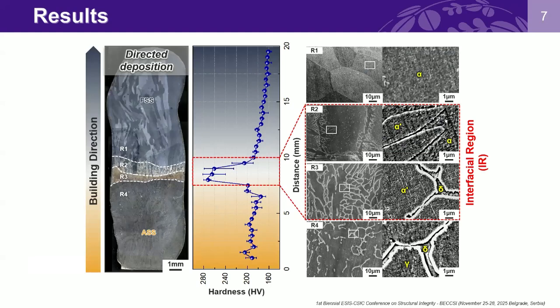So let's move on to the results part. The macroscopic overview, hardness profile, and microstructural distribution of the directed deposition sample are displayed in this slide. The hardness in the interfacial region exhibits an evident enhancement compared to the austenitic stainless side and the ferritic stainless side.